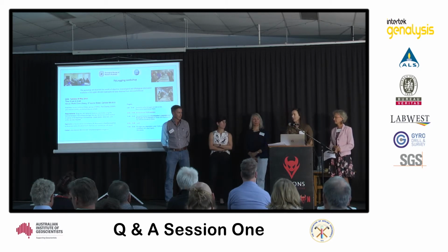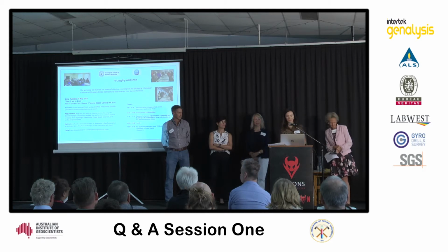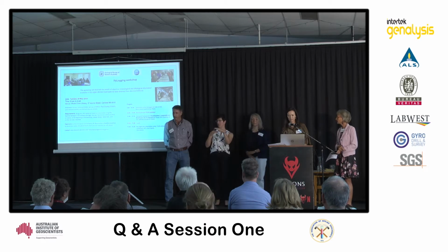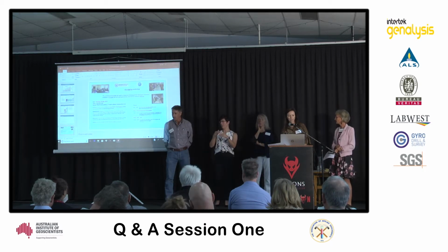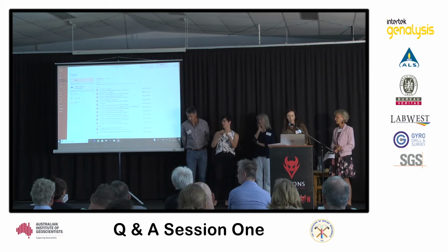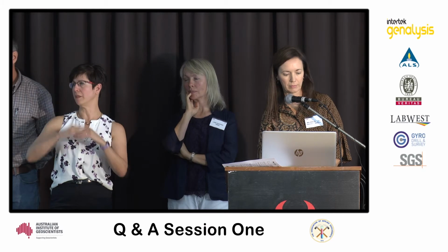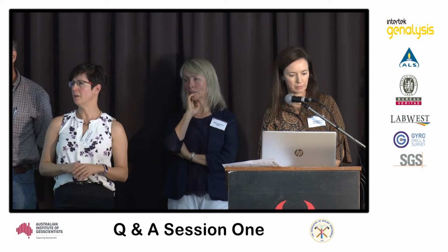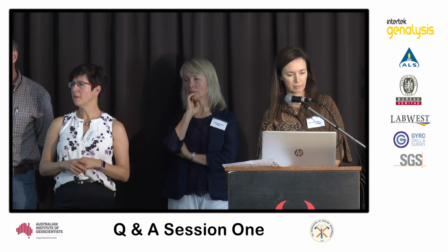I actually have a slide that I hid because I had to chop out slides. Can I show that to answer the question? See, what happens is that, just while Melissa's finding that, the finer the grain size, the more reflection you get off the surface of the sample. So the less penetration. So basically the features become smaller and weaker, but the brightness increases. So you just get features that are closer to the noise, really, with the really fine powders.